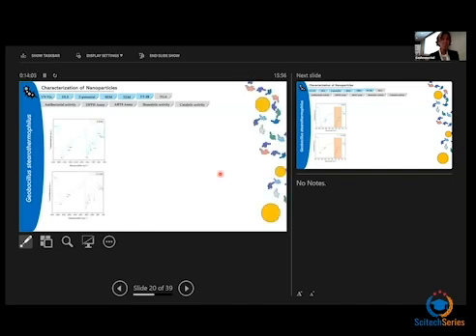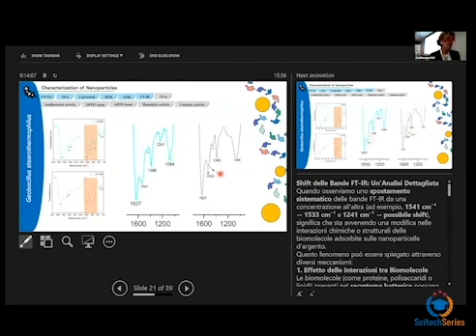Also, when looking in more detail at the fingerprinting region, we could observe that at lower precursor concentration the molecules look more able to vibrate and less densely packed than in the other sample, suggesting that there can be different coatings using different conditions.